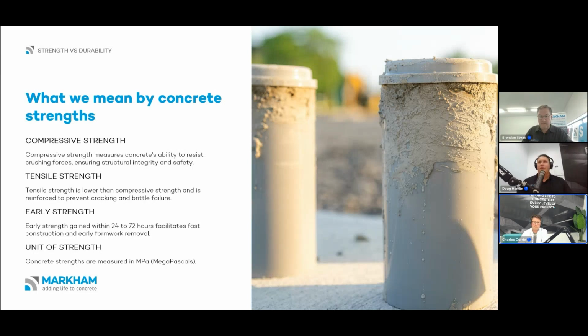Now, tensile strength is essentially the other way around. Rather than looking at the pushing force, it's looking at the pulling force. So that's concrete's ability to withstand being pulled apart or being flexed, and how that's done is that same cylinder is put on a machine and pulled until the point that it breaks. And then that is known as the tensile strength. So normally, say if you've got a 40 MPa compressive strength, your tensile strength's normally about 10% of your compressive strength, as a general rule of thumb.